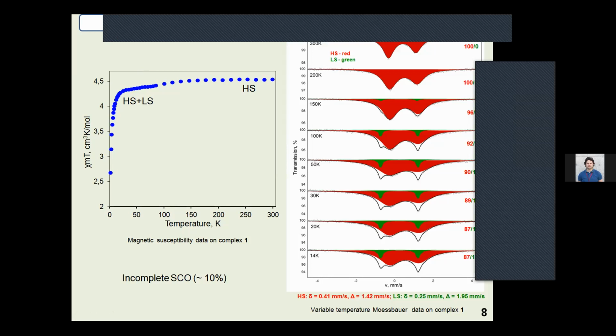Mössbauer spectra at high temperature exhibit a well-resolved quadrupole doublet comparable with the corresponding high spin ferric state. Subsequent lowering of the temperature is accompanied with the appearance of another quadrupole doublet in addition to that observed at 300 Kelvin, which is characteristic for the low spin ferric isomer. The ratio of intensities of two signals was estimated as 90% to 10%, indicating incomplete spin crossover.